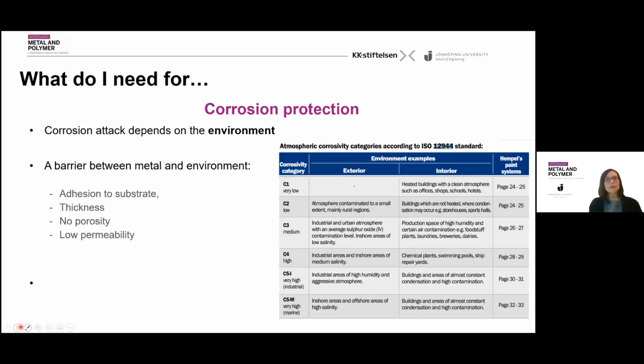Which level of those 4 parameters do you need? Well, that depends on the atmospheric corrosivity. Different environments will attack the component at different grades. To define how aggressive an environment is, there is an international standard that helps you: the ISO 12944 divides the atmosphere into 5 classes, depending on how aggressive that class is. If you enter into the standard, you will find a description of the typical conditions for each aggressivity level, and also a way to define and measure the aggressivity of an environment.